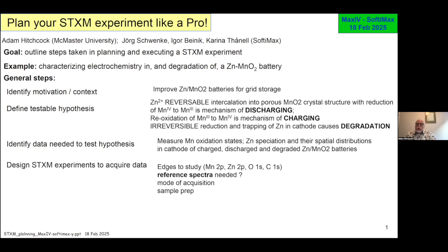It was just a question of making samples that are the appropriate thickness, which are the order of a few hundred to a half micron for the energy ranges we were interested in. And sample prep is always an issue, and you will see that the content of this part of the talk on the zinc ion batteries was very much an issue of feeling our way to get the optimal sample preparation. So the next step is